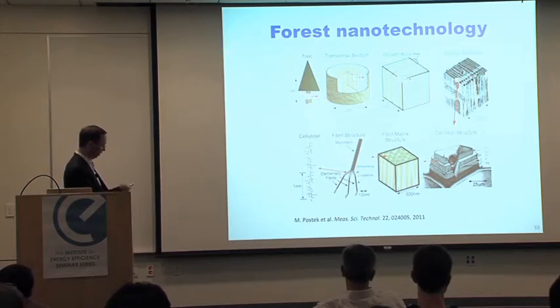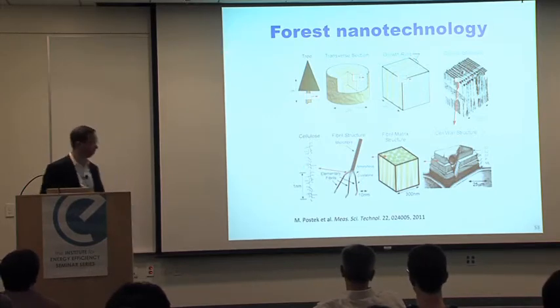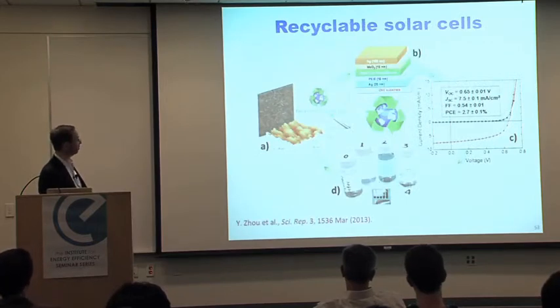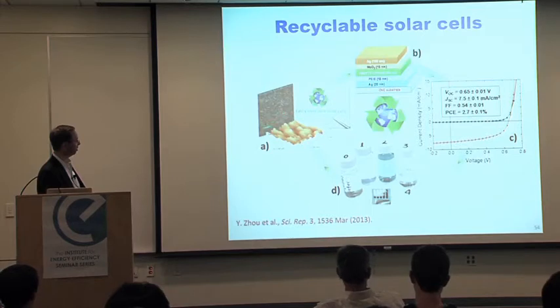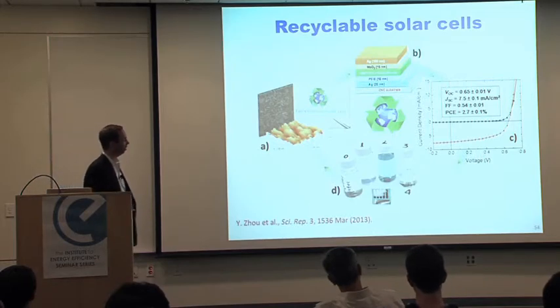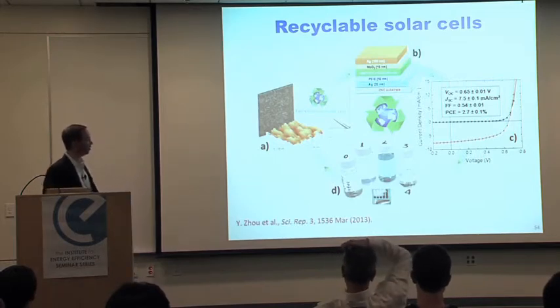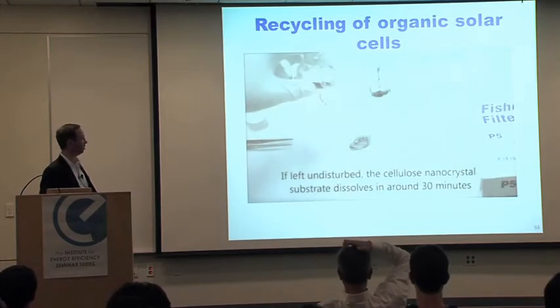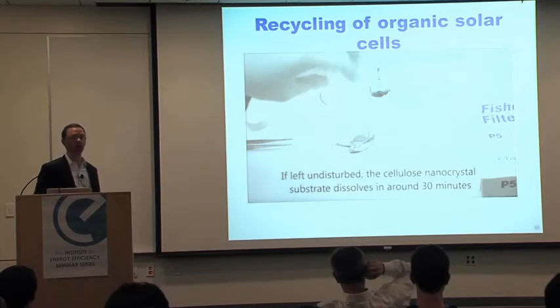And if you blend some of these cellulose nanocrystals with some glycerol, you can fabricate transparent films. You barely see the film here on the tweezers. It's fairly optically transparent, but more importantly, it's very flat. The surface roughness is down to a few nanometers, and so we could build solar cells on devices like this. Efficiencies now are about 4% in these devices, but what was interesting to see is the ease of recycling of these materials.